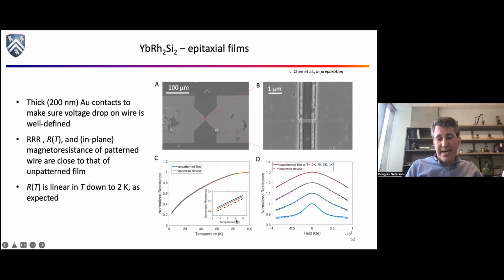And in fact, you can see at low temperatures, it's linear in T, okay, as the strange metal is supposed to be. Probably a better test is you can look at the resistance as a function of magnetic field. I'm actually not sure why this has the shape it does. But again, you can compare the nanowire device to the unpatterned device, and you see that basically nothing has changed by the patterning. So that's how you know a couple of things. That's how you know that the resistance you're measuring is really dominated by the wire, not by the pads. And it's also how you know you haven't ruined the material by patterning it.